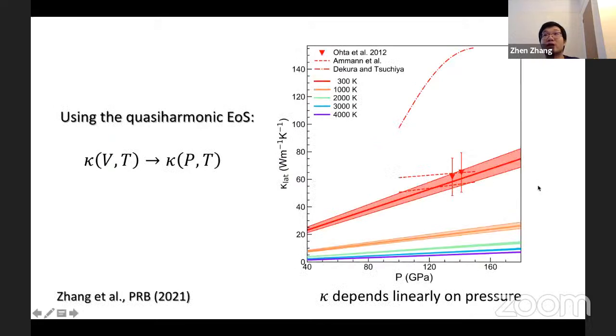For more practical use by geoscientists, kappa as a function of pressure and temperature is desired. Therefore, kappa of VT was converted to kappa of PT by utilizing the quasi-harmonic equation of state. The obtained results are shown on the right. A noticeable feature for kappa is that at constant temperature, it depends linearly on pressure, which is a typical feature for lower mantle minerals observed by both experiments and computations. The calculated kappa at room temperature compares well with available experimental results, also at room temperature.